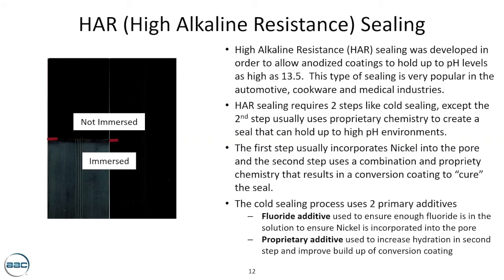Earlier I mentioned the immersion time in a cold seal. When you're doing high alkaline resistance and you're trying to achieve a pH of 13.5 environments, this is a scenario in which your cold seal immersions may be longer than the 7 to 10 minutes we mentioned earlier. Because of the nature of the application, sometimes these cold seal steps can go up to 15 to 20 minutes and then be followed by a subsequent step that's another 15 to 20 minutes. The intent of that total seal time being as much as 40 minutes is to create a part that, when immersed in a bath of 13 and 13.5, which is essentially caustic, doesn't strip and can hold up to it.